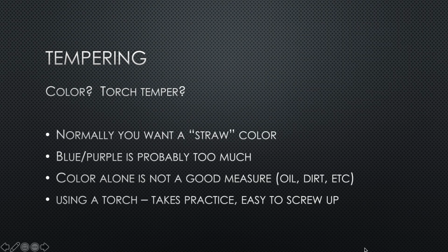So you hear people talk about color and torch tempering, and yeah, normally you want a straw color. If it's blue or purple, it's usually way too hot, but color alone is just not a good measure. There can be oil, especially after a quench. I don't typically clean mine completely after a quench, so there's oil and fingerprints and all kinds of stuff on it. So really, color is not a good measure, guys.